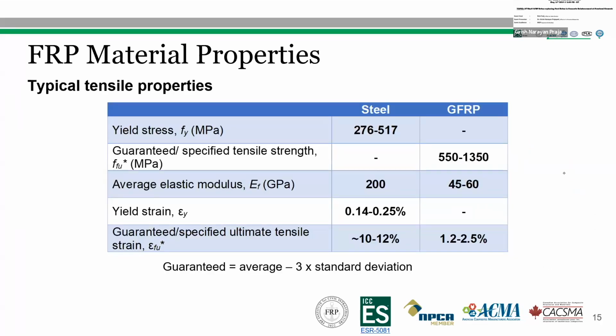Since the glass fiber reinforced polymer bar doesn't have any yield point, the guaranteed tensile strength of GFRP bars varies between 550 to 1350 megapascal. The guaranteed tensile strength is found by subtracting 3 times the standard deviation from the average tensile strength. The GFRP bar has a lower average elastic modulus, varying between 45 to 60 gigapascal, and the guaranteed ultimate tensile strain of GFRP bars varies between 1.2 to 2.5%. Generally, this variation depends on the amount of fiber and resin content.